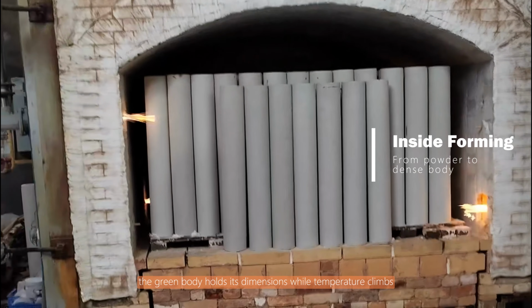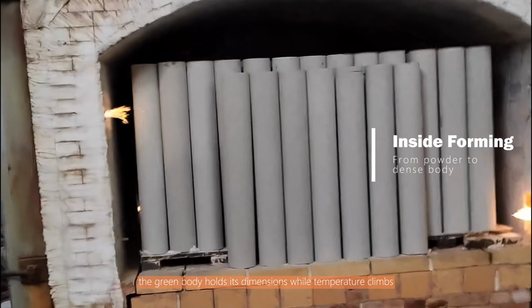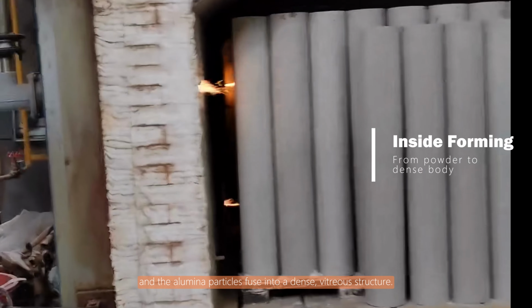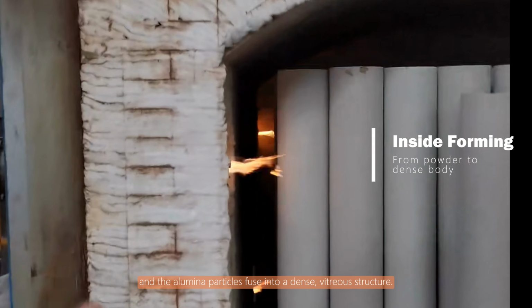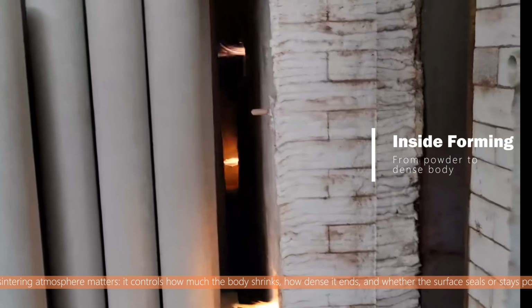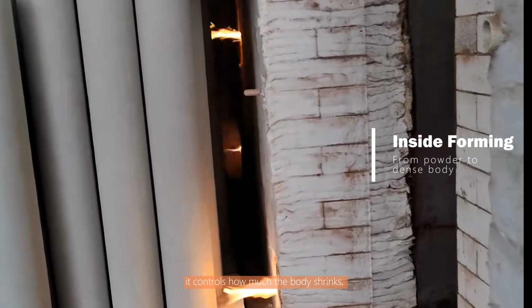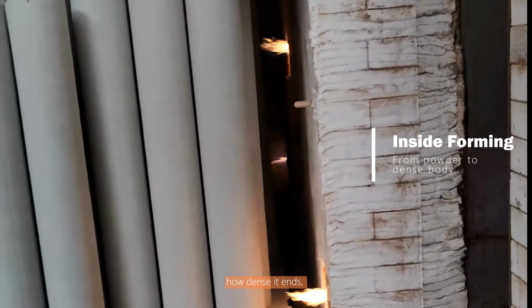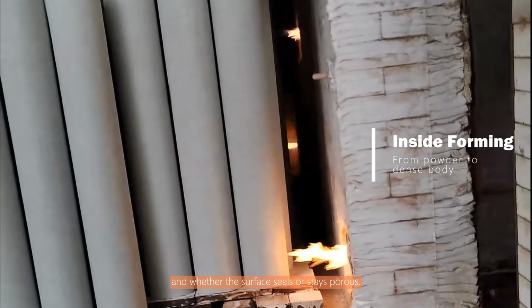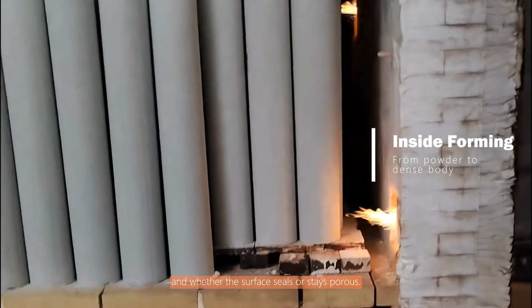Then sintering. The green body holds its dimensions while temperature climbs and the alumina particles fuse into a dense, vitreous structure. For 99.7% material, that sintering atmosphere matters. It controls how much the body shrinks, how dense it ends, and whether the surface seals or stays porous.